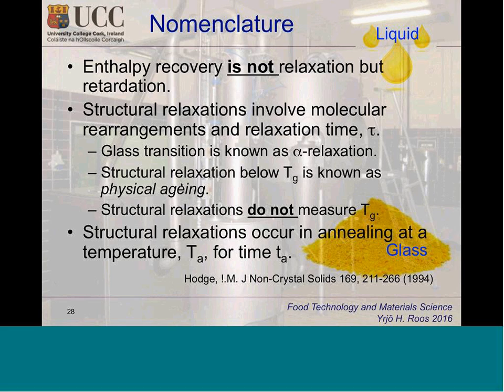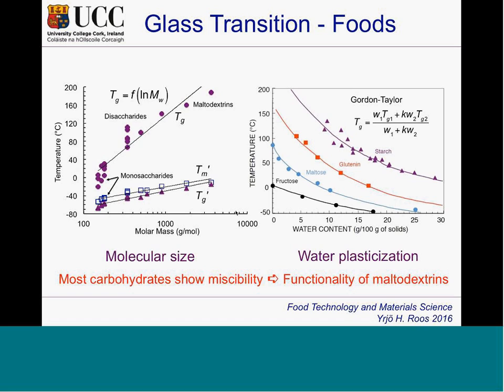So relaxations don't really measure the glass transition. We have to keep in mind, if you do measurements of properties about the glass transition, you are probably measuring something related to the relaxation times rather than the glass transition itself. Sometimes there are misconceptions on that. And we need to do annealing thermal treatments to find what is happening.